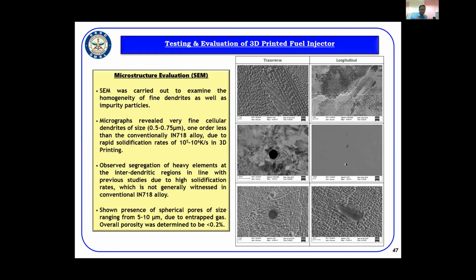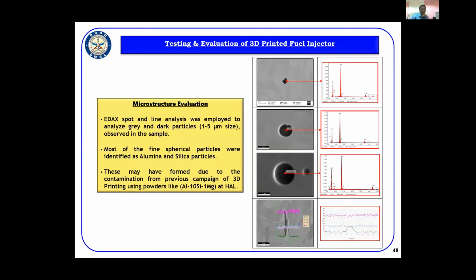Then spherical pores were also formed in the microstructure, which we could not understand at first. We thought that these were all entrapped gases. The overall porosity was determined to be less than 0.2%. To understand these impurities, further analysis was carried out using EDAX spot analysis to analyze the gray and dark particles. What we found is that the fine spherical particles were identified as alumina and silica particles, which are not present in the 718 alloy.